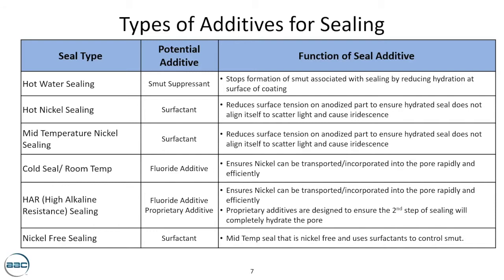So what many individuals do with hot water sealing is they use a poison to hydration, or an additive that stops hydration, to prevent that smut from forming. Now, the trade-off there is in doing so, you may not get a good seal, but you will get a reduction in smut. And I'll go into that further on subsequent slides.